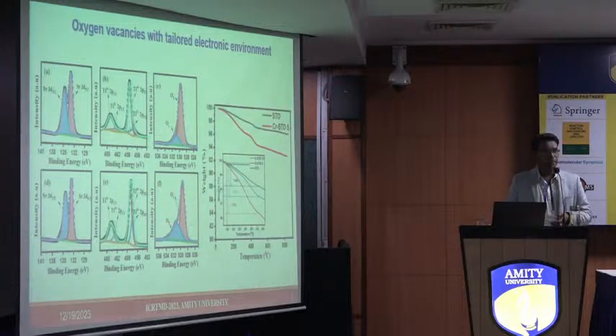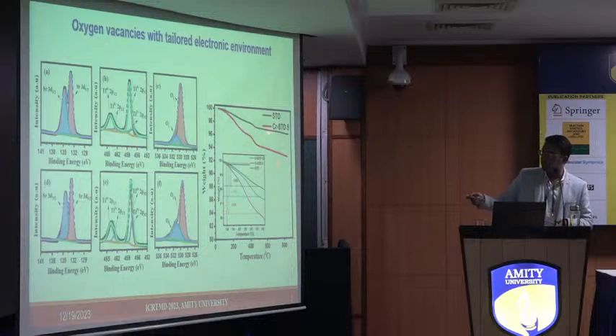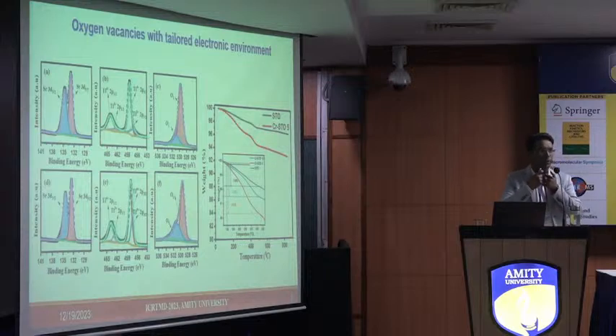We have also quantified these oxygen vacancies using a very simple technique, thermogravimetric analysis. You can see that the weight loss corresponds to the coordinated waters which are there on the oxygen vacancies. The higher the weight loss of the coordinated water, the higher the number of oxygen vacancies.